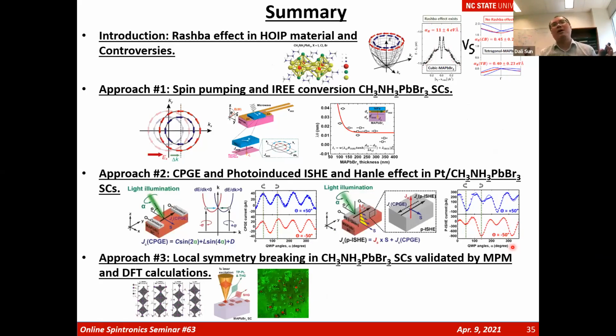So that's my summary for my talk. I introduced the Rashba effect, the hybrid perovskite, why it's interesting for spintronics, and also the debate with the positive responses and negative responses. We confirm the Rashba state in hybrid perovskite material using three techniques: spin pumping, CPGE, and photo-induced ISHE, and we also confirm the local symmetry breaking on the surface of the single crystal by the second harmonic generation, supported by the DFT calculations. So this summary concludes my talk.